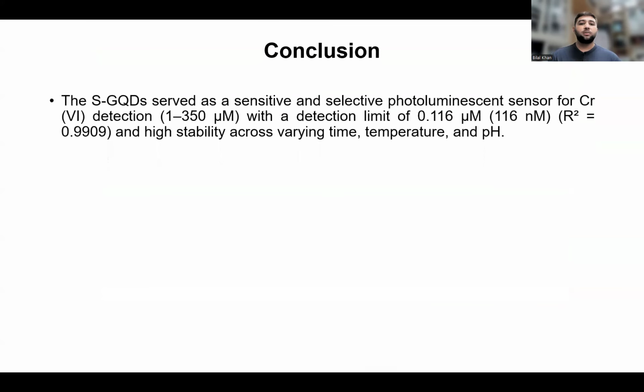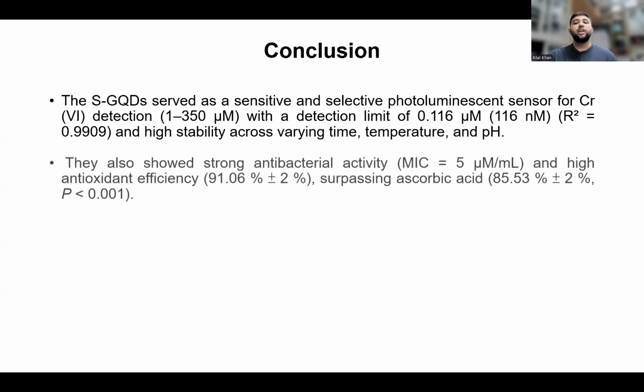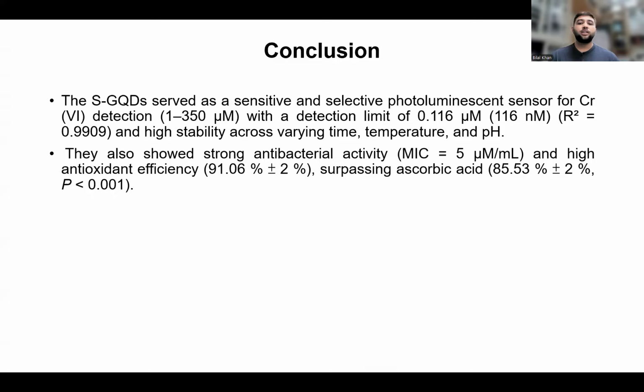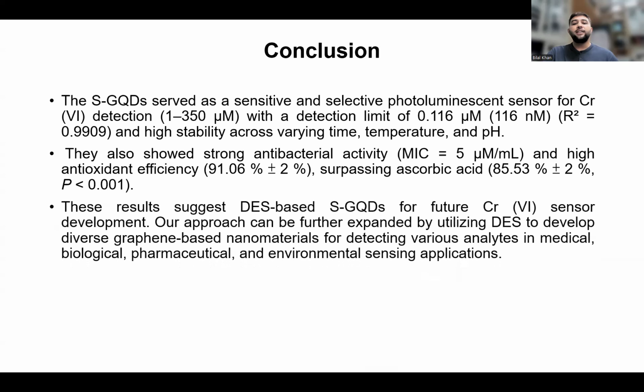The sulfur-doped graphene quantum dots serve as a sensitive and selective luminescent sensor for chromium-6 detection in the wide range of 1 to 350 micromolar with a detection limit of 116 nanomolar. It also shows high stability across time, temperature, and pH. They also showed strong antibacterial activity with an MIC of 5 micrograms per ml and high antioxidant efficiency of 91% for sulfur-doped graphene quantum dots, while ascorbic acid was lower, at 85%. These results suggest DES-based sulfur-doped graphene quantum dots for future chromium-6 sensor development.